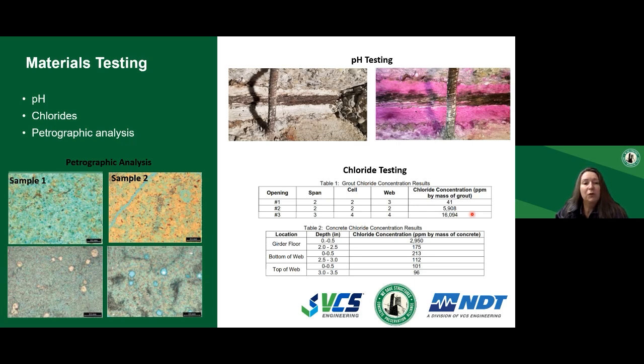Typical thin sections from petrographic analysis are shown on the left side of the slide. Here we have 2 different samples that were collected from the same project. Petrographic analysis is typically used to verify that the grout is cementitious. It can also determine the presence of supplementary cementitious materials and also give us a comparison of the water to cement ratio in different samples.